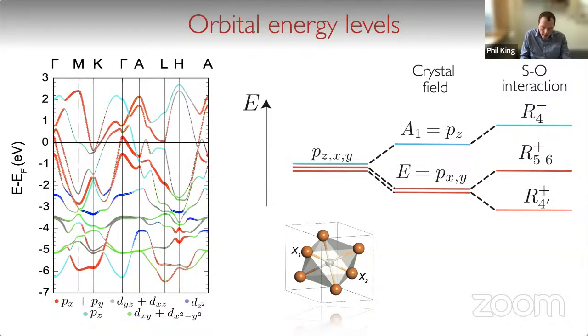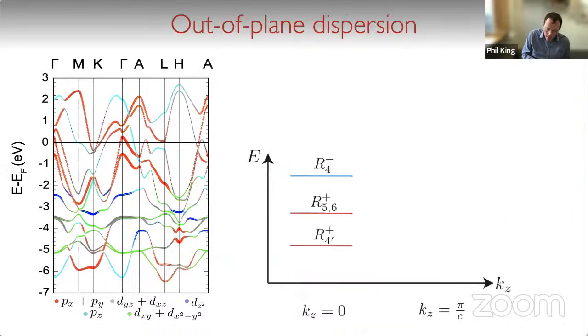Now we're dealing here with tellurium p orbitals, and so we also have a strong spin orbit coupling in the material here. And so we need to consider the influence of that. And that will shift in energy the pz derived states, but also split apart now the px and py states into a pair of states that you can see here. Okay, so this is then our starting point for thinking about the electronic structure. And we can ask how these states should disperse throughout the three-dimensional Brillouin zone, in particular thinking along the gamma A direction, or the 0 to pi/c direction of the Brillouin zone.